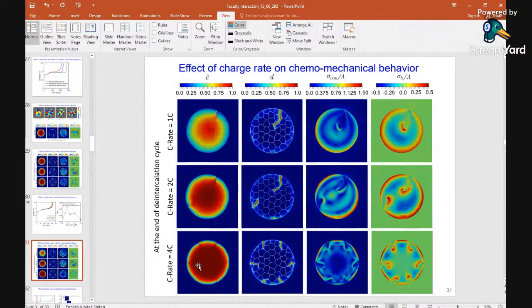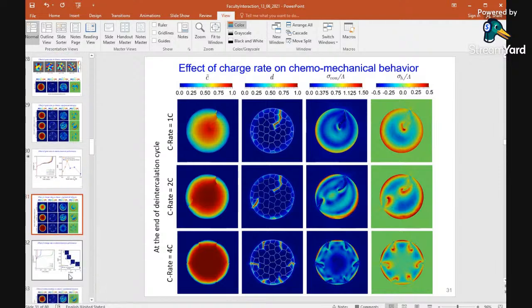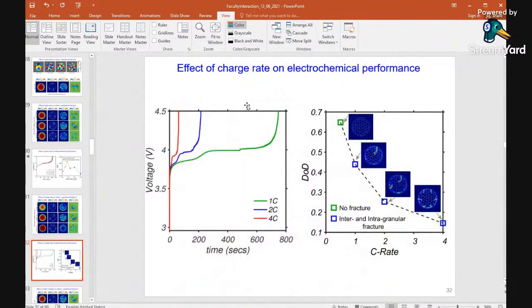But the crack doesn't propagate inside, because it doesn't get enough driving force. Once the crack is generated, the material loses elasticity in those regions, so it doesn't allow the crack to propagate. It doesn't keep enough driving force. So this is the detailed map. We can get much more detail in the publication. Then we can really map.